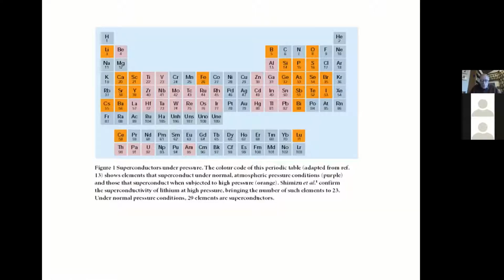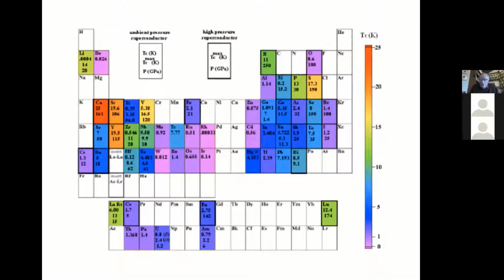So another way to look at this diagram is in terms of what the superconducting temperatures are, and this is some scale here for where color is supposed to be saying something about what the TC is. And if you look at this, there doesn't seem to be any systematics about where the highest TCs show up as you go across with, for instance, a variable such as electrons per atom that Matthias so liked to use in the study of superconducting transition metal materials. It's also interesting to me the fact that, of course, the really good metals like copper, silver, and gold just are not superconducting at all.